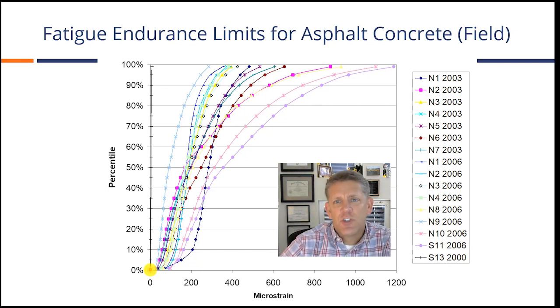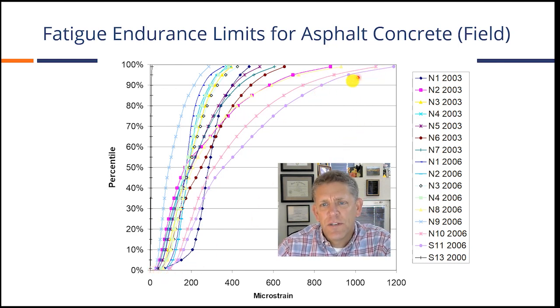And what this plot is showing is data from our NCAT Test Track. What it's representing here is the range of strain levels, that tensile strain that has been measured inside of the pavement section of the test track. In some of our sections, we instrument them so we can make measurements of strain. So rather than predict it, we just measure it directly under traffic. So this is the range of strain levels, and then this is the cumulative percentile.